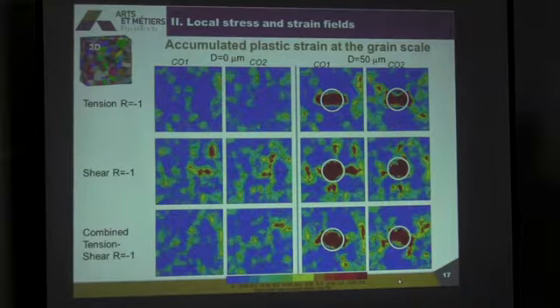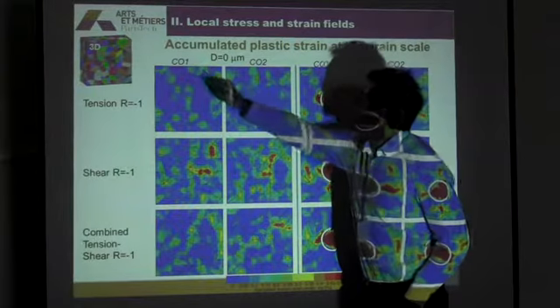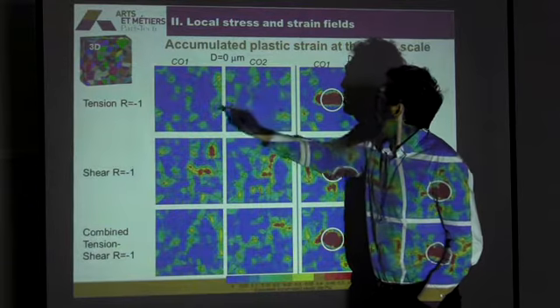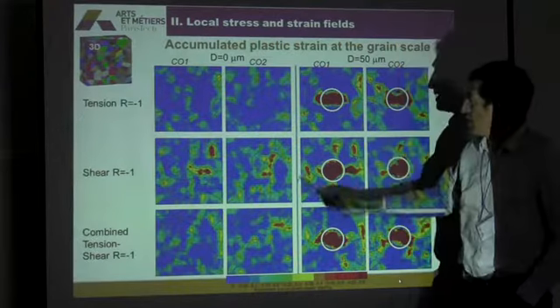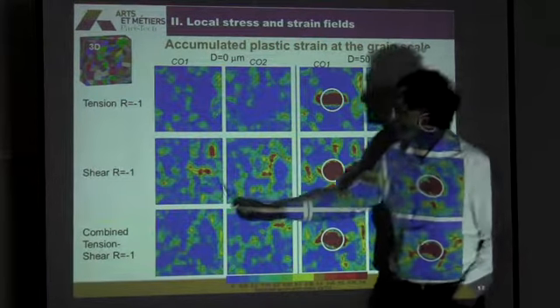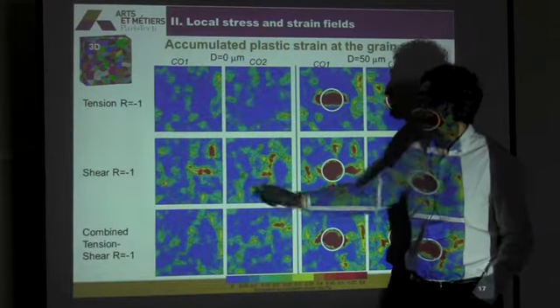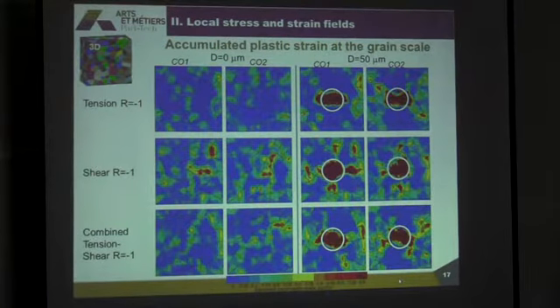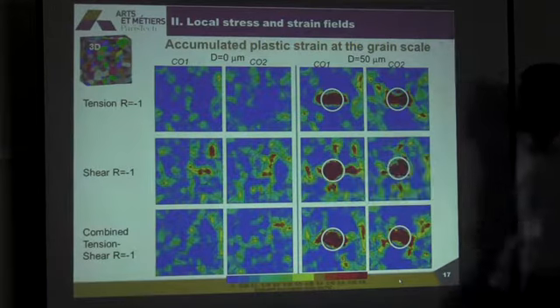If you take a closer look, you see that the grains have the same morphology here and here. And when, for instance, in the case of the shear loading, you move to this crystal orientation to this one, you clearly see that the grains that suffer the higher plastic strain are not the same. So there are strong effects of this crystallographic orientation.